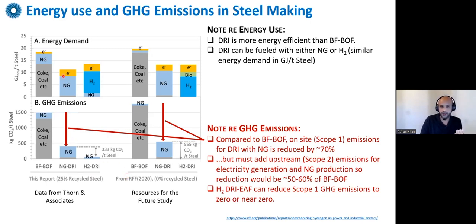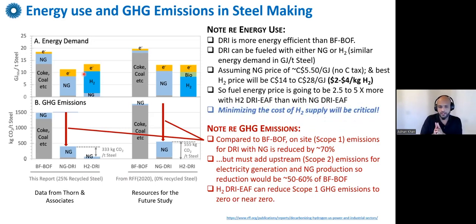Now, compare natural gas DRI versus hydrogen DRI. Let's talk about this transition, which is going to happen in the Dofasco plant, which we're envisioning. Assuming a natural gas price today of $5.50 a gigajoule, and at best case scenario, if you assume a hydrogen price of $2 to $4 a kg of hydrogen, which is basically about $14 to $28 a gigajoule. What strikes you straight away is that the fuel energy price with this transition from natural gas DRI to hydrogen DRI will mean that your energy cost will be 2.5 to 5 times more with this transition to the hydrogen DRI.